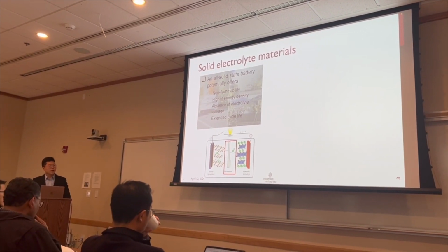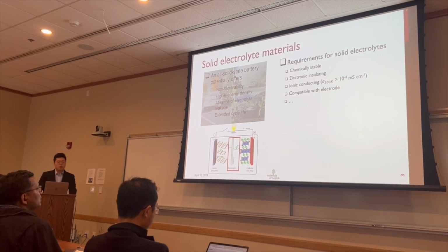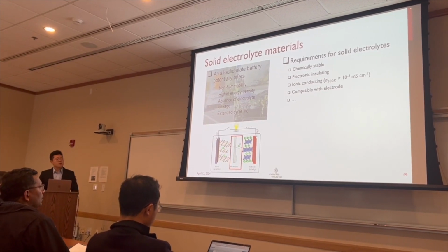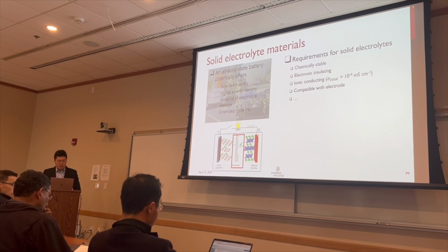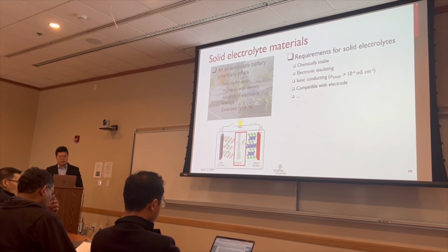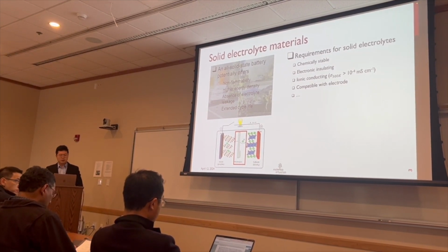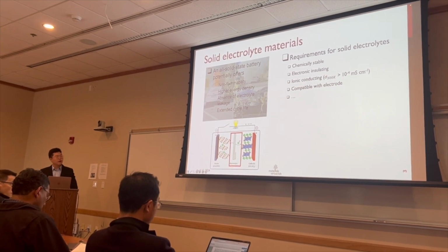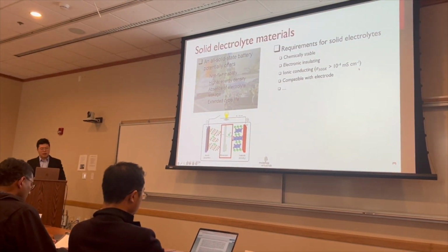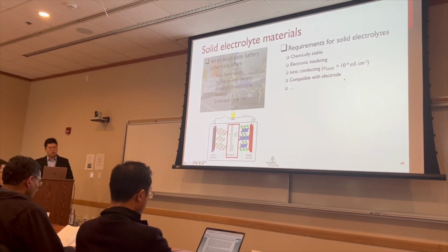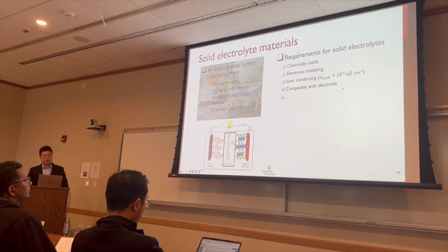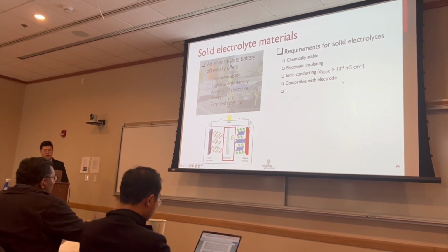Those solid electrolyte materials have several requirements. To begin with, it needs to be synthesizable, and it also needs to be electronically insulating to prevent short circuit between electrodes. And it needs to have high ionic conductivity to do fast transport of mobile ions between electrodes. And it also needs to be compatible with the electrode so that there's no degradation happening during cycling.